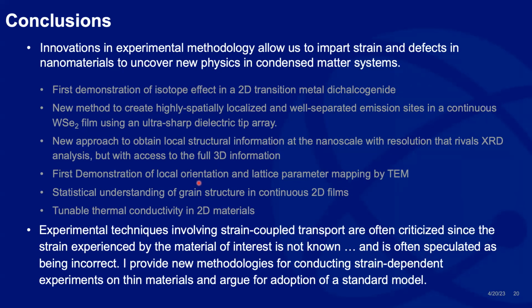So we have ACOM in the TEM, and that code is active now, and those techniques are active now. We've modified the apertures in our TEM to do that. And we have statistical understanding of the grain structure analysis in continuous 2D films grown on amorphous substrate. We do see a preference for misorientation of about 8 degrees. And then, this I didn't show, but we have tunable thermal conductivity in 2D materials, which is related to some of the stuff I was talking about with Miguel.